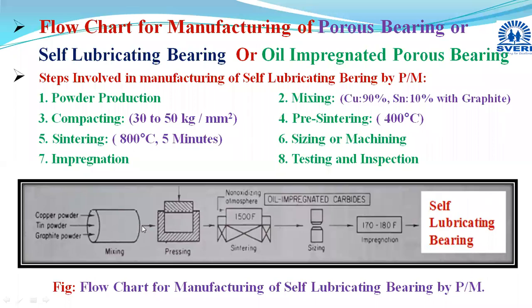And after this, we are moving to the next stage. This is the flow chart, and the next stage is pressing. This is the symbol for the pressing or compacting stage. This is the die cavity, and this is the punch, and we are applying pressure. Here you have to mention the compacting pressure value. In this compacting stage, the uniform and homogeneous mixture obtained in the mixing stage is poured into the metal die cavity with the help of a feed shoe or a hopper. Powder volume is adjusted by raising or lowering the lower punch or lower plunger of that metal die cavity. After filling it completely, you have to level it with a sweep of the feed shoe, and after that the pressing is done.